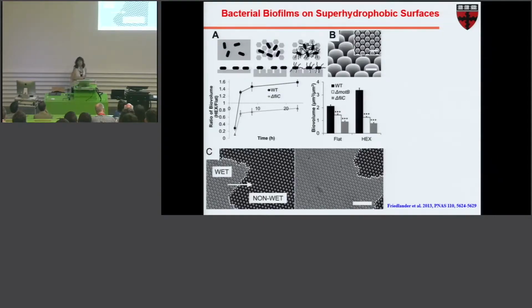And there are multiple reasons for that. One of the reasons is that for a surface to stay superhydrophobic, it has to be hydrophobic. But biological matter, in particular, though not only biological matter, will be able to change the surface chemistry. With time, the chemistry of the surface to which it is attaching is constantly changing the contact angles and the type of wettability it creates. So the outcome is that all these crevices that were not available before now become available. So the surface to which bacteria can attach, as it changes the surface chemistry with time, is higher than on a flat surface. So the outcome is that it now has higher biomass accumulated on these surfaces.